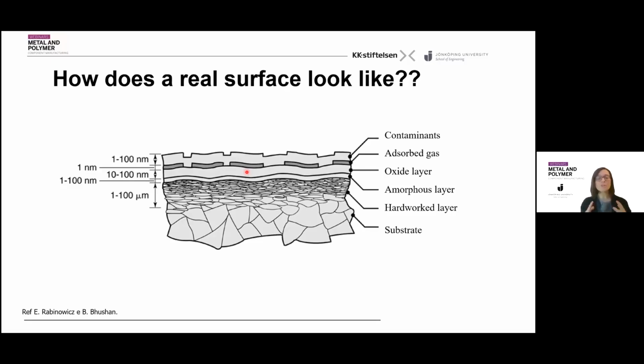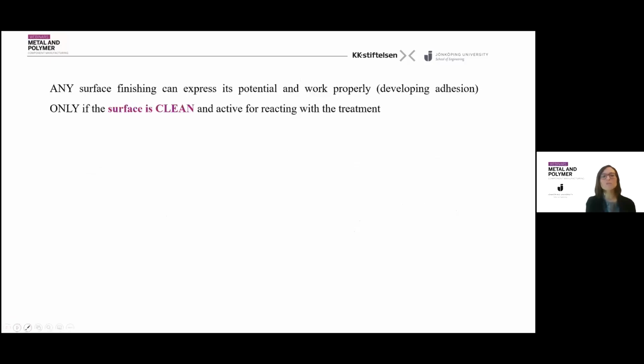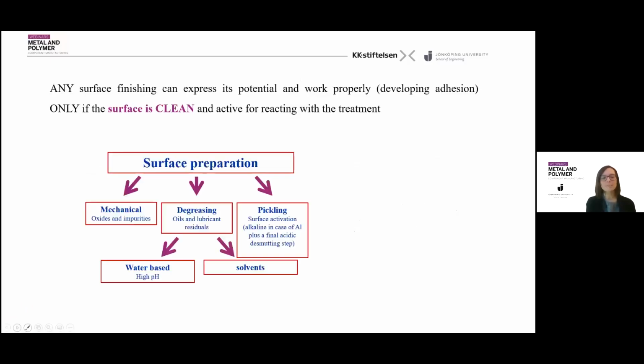So you can understand that such a surface cannot be ready to form new bonds with the material we want to add as a coating. Therefore, the most essential step in our strategy for durability is to design a cleaning step. We need to prepare the surface to remove those layers in order to expose fresh aluminum to form bonds in coating. So any surface finishing can express its potential and give the performance you're looking for only when we clean the surface.